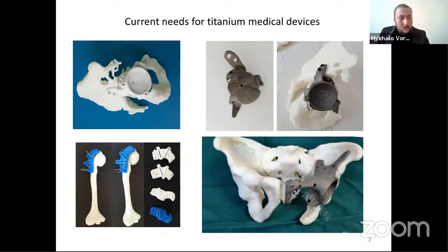All my excuses for this. Thanks. Our team was inspired by the most difficult and responsible titanium parts for medical application. We tried to obtain something like this, not by using additive manufacturing, but using casting technology. Now such details are usually obtained by 3D additive manufacturing, but we believe and even are sure that in some cases thin-walled titanium castings may be much better and more reliable than sintered powders.